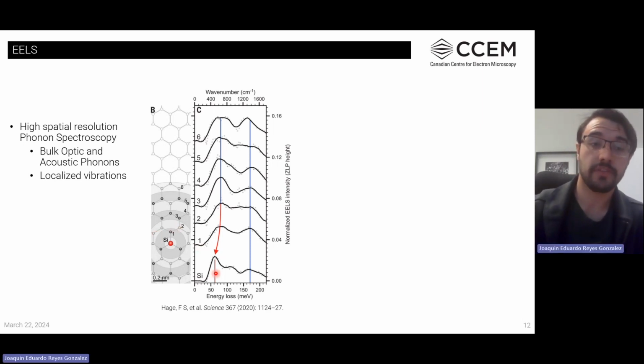And here you can observe what happens: with a very small probe at the Angstrom level, sub-Angstrom level, by locating it on the silicon atom and then moving towards the neighboring carbon atoms, farther and farther away from the silicon, it is possible to extract the vibrational EELS, the phonon EELS, associated with the silicon atom and how it affects its neighboring atoms.